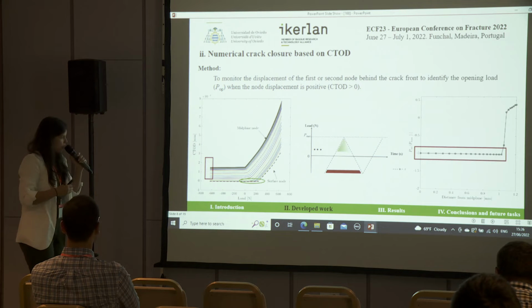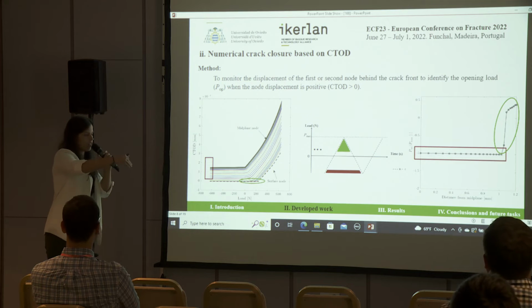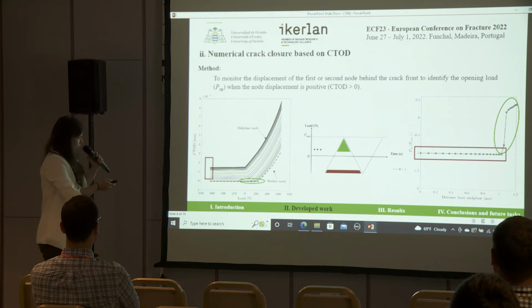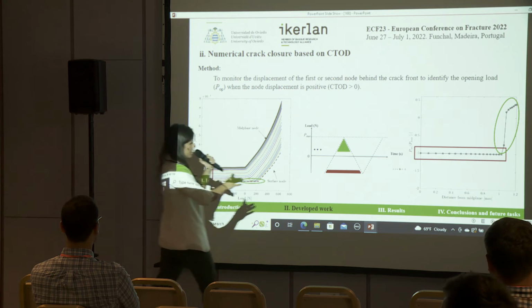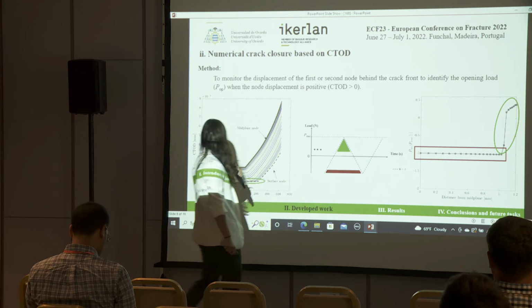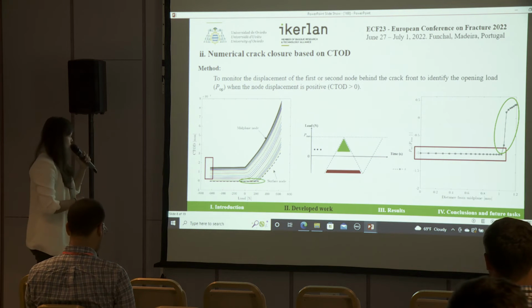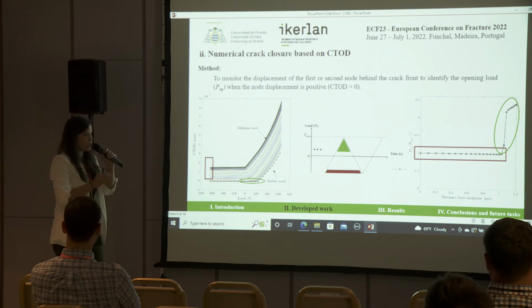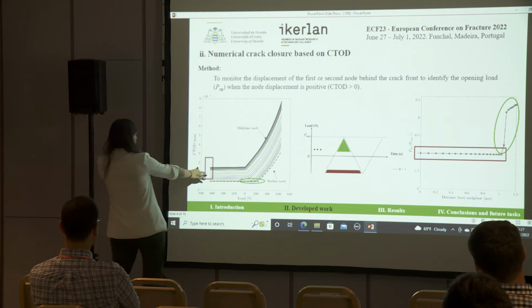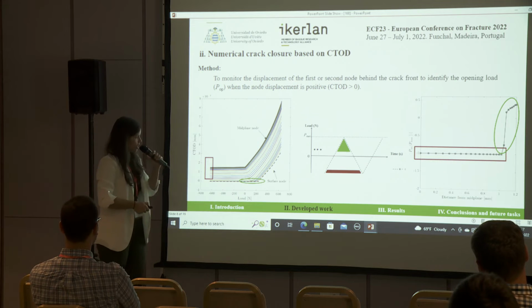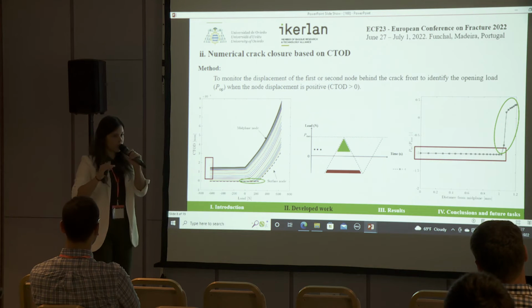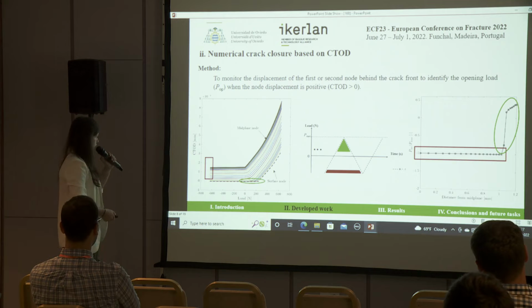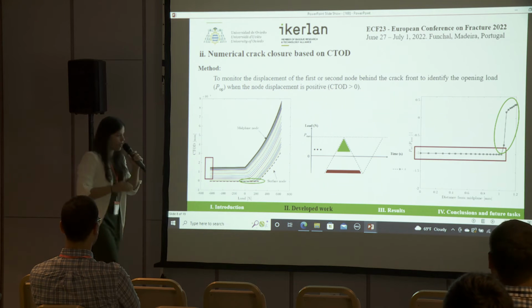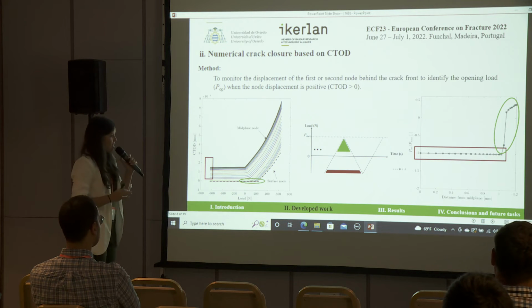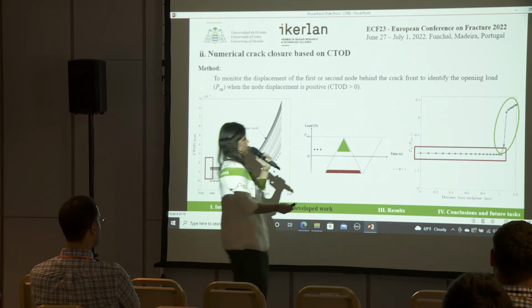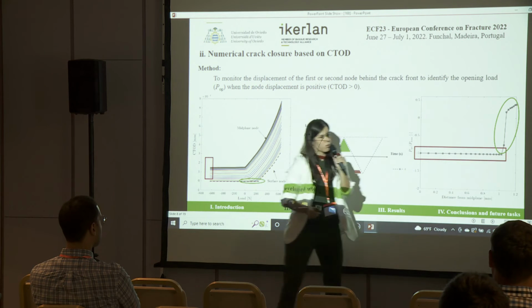So, repeating this procedure for the rest of the crack along the thickness, the crack closure distributions through a thickness can be obtained as follows. Moreover, here you see that most of the nodes are already open under the minimum load and have a constant value equal to the stress ratio. However, the surface nodes here are progressively opening, which indicates that the crack closure was located here, close to the surface.